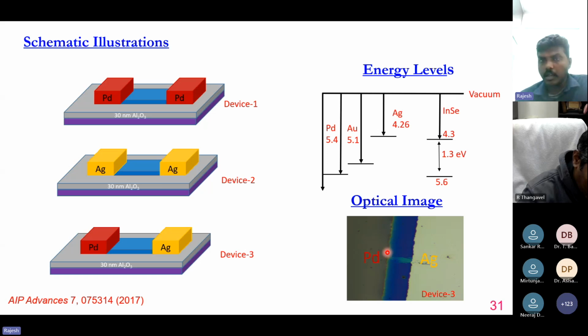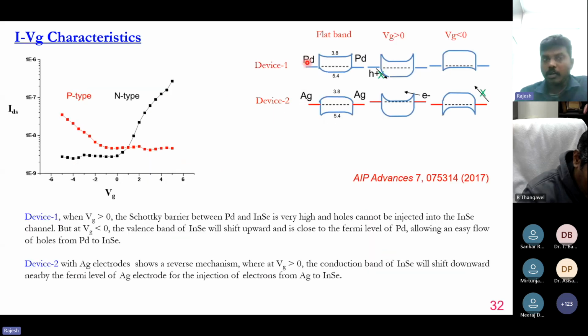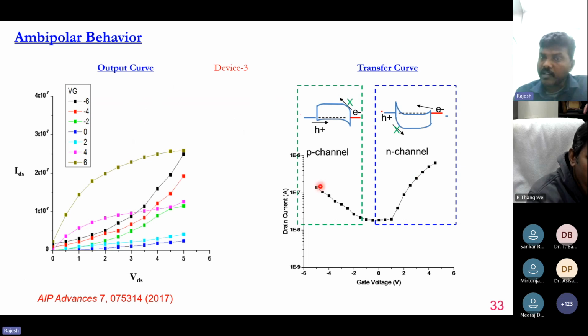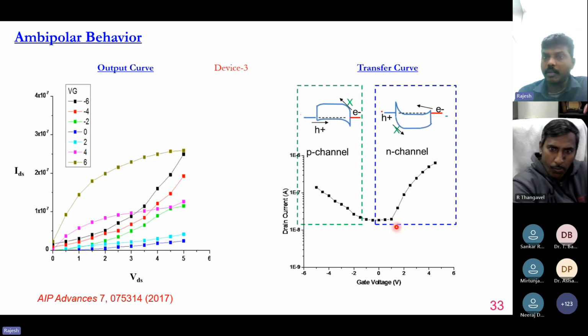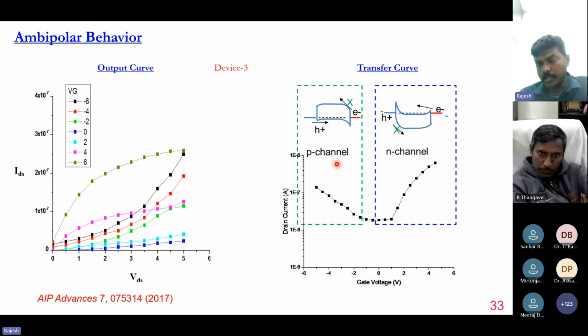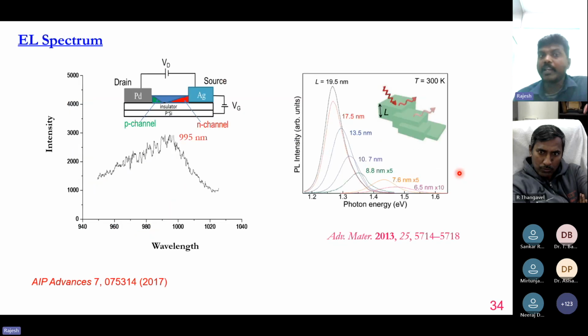In this case, on one side we are able to inject electrons, and on the other side we are able to inject holes. So you can clearly observe we are able to get both p-type as well as n-type behavior due to the palladium and the silver. We clearly observe ambipolar nature with the help of palladium and silver. By having this electron and hole injection, recombination happens in the indium selenide.